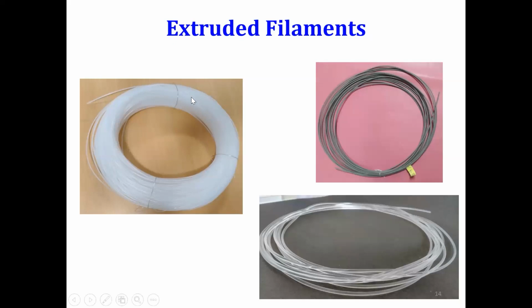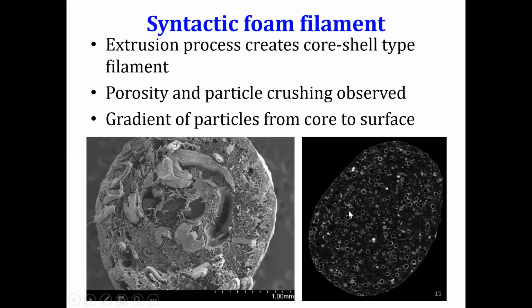So this is the filament of 1.75. Then we infused environmentally polluting fly ash cenospheres in that. We were able to get this. We have printed some composites, some elastomers as well. So this is the elastomer, which is used for steering wheels in four-wheelers. We have developed some blends and printed them as well.